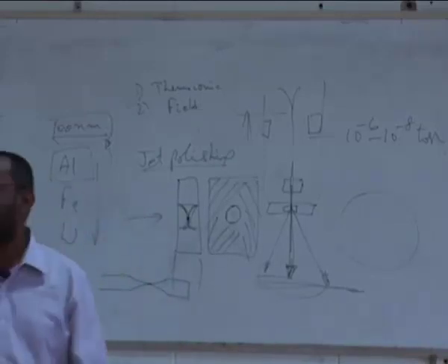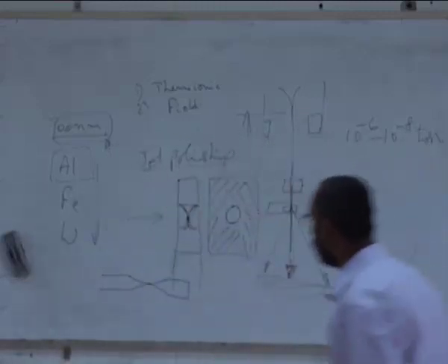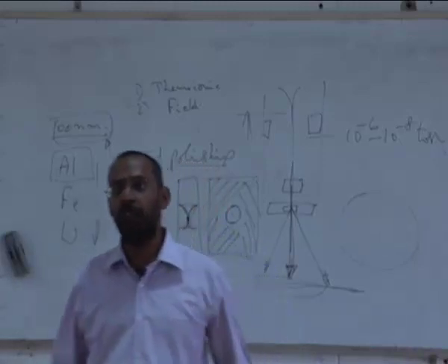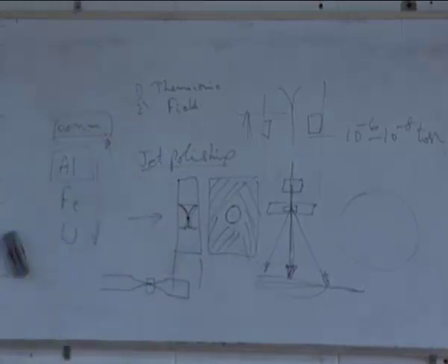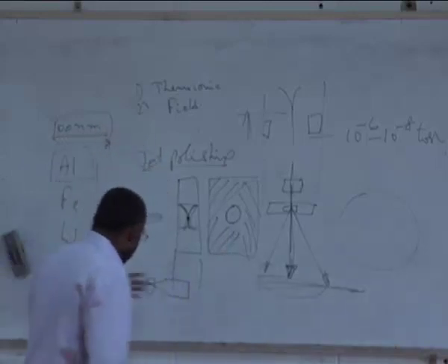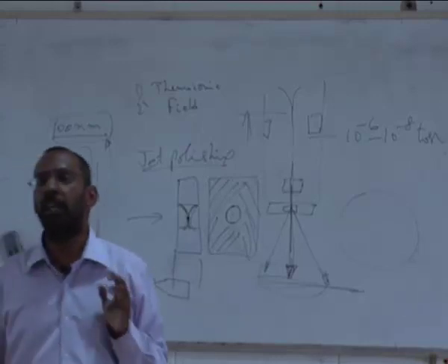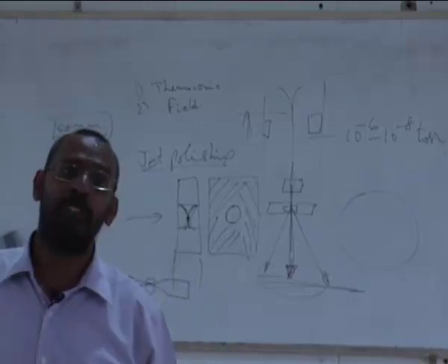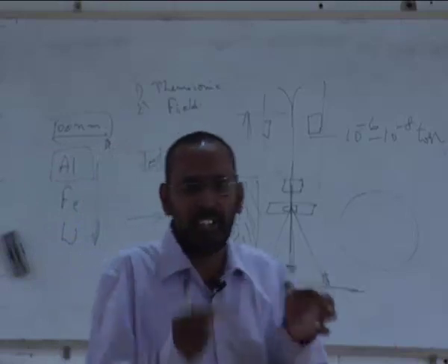If you have ever seen a sample that is prepared for tensile testing, they prepare samples like this. If I concentrate on this region in my microscope, I will see that the thickness in this region will be of the order of this, because everything got thinned. This is happening continuously, and at some stage the moment the hole is formed, you can stop. But the problem is, how do I stop immediately after the hole is formed? This is a major challenge. You need to be very careful to catch it just when the hole has formed.